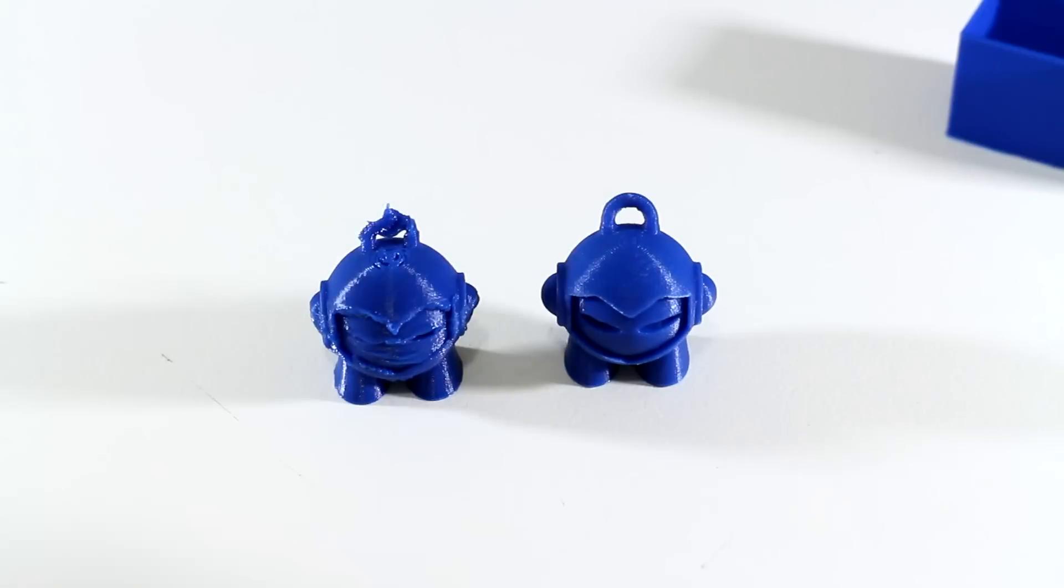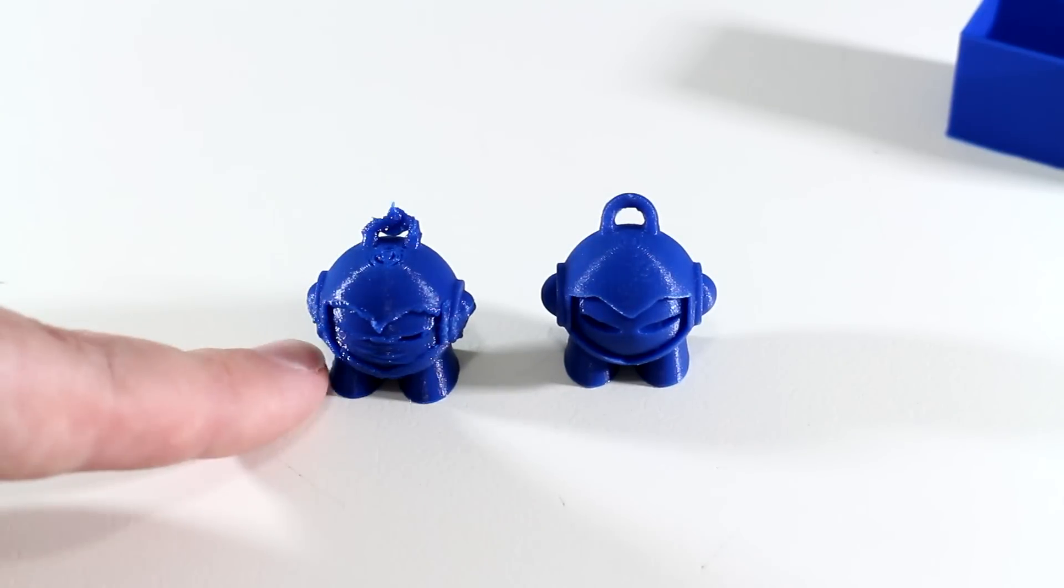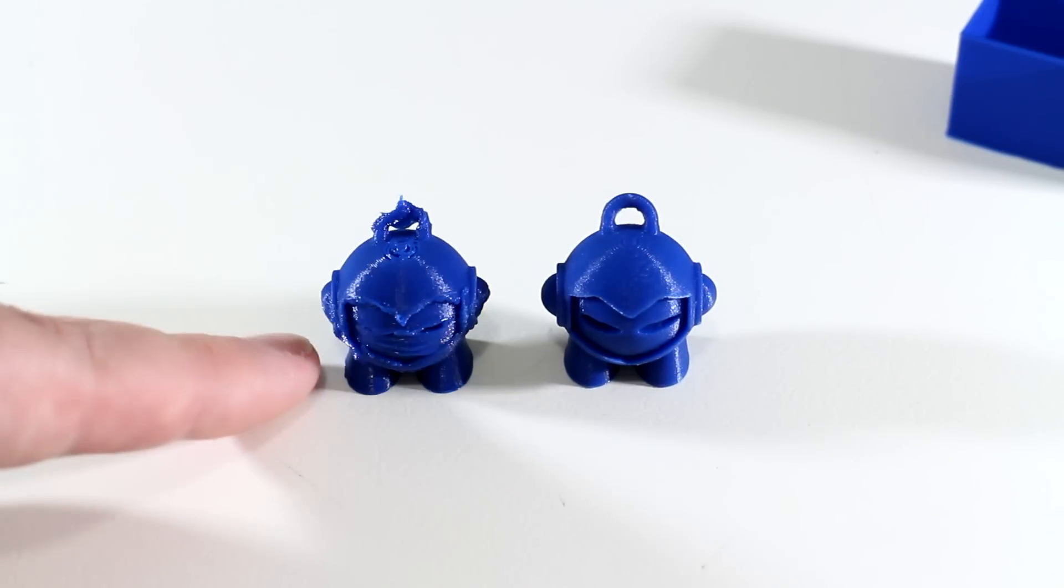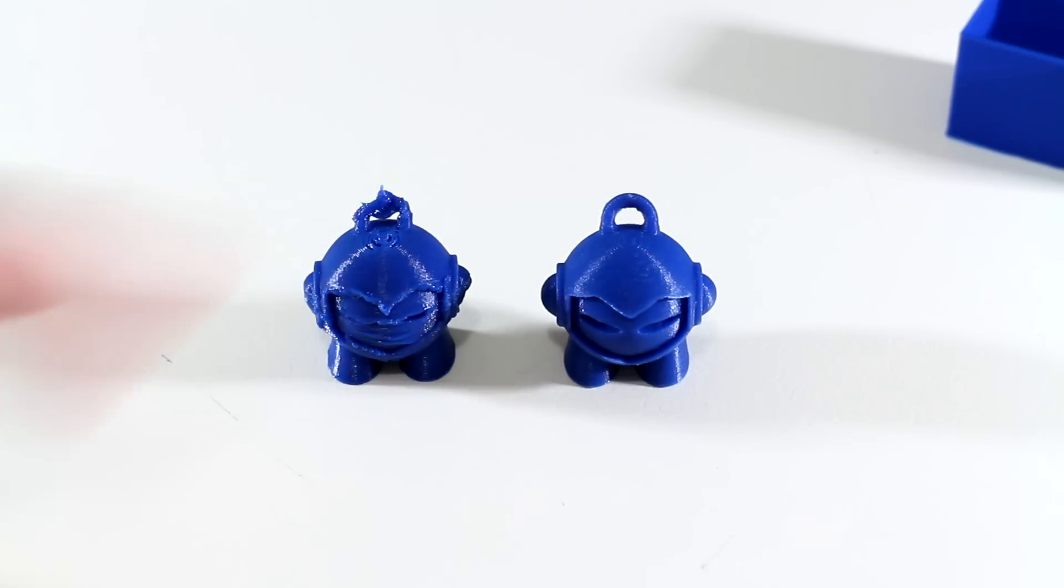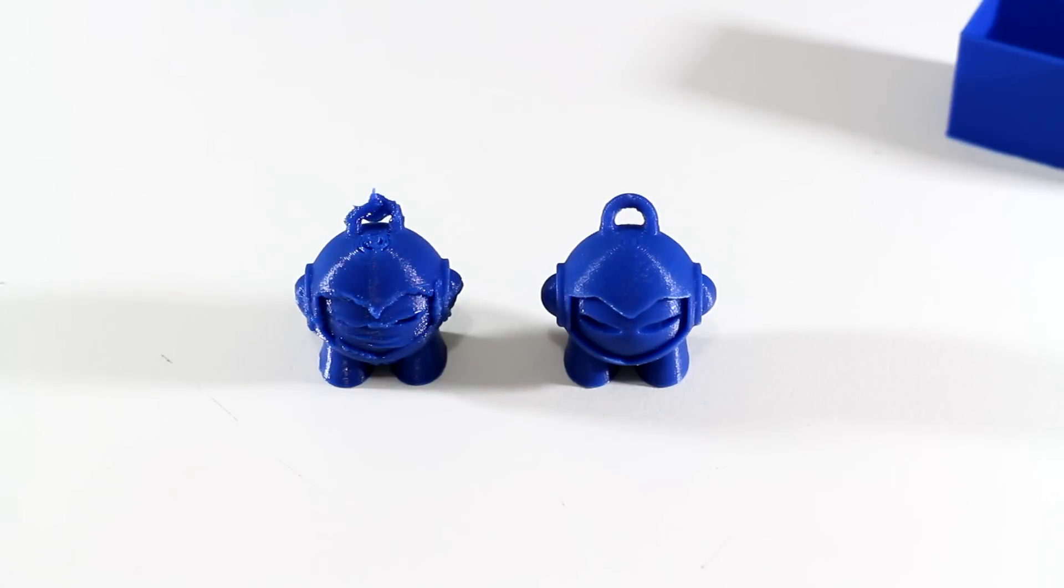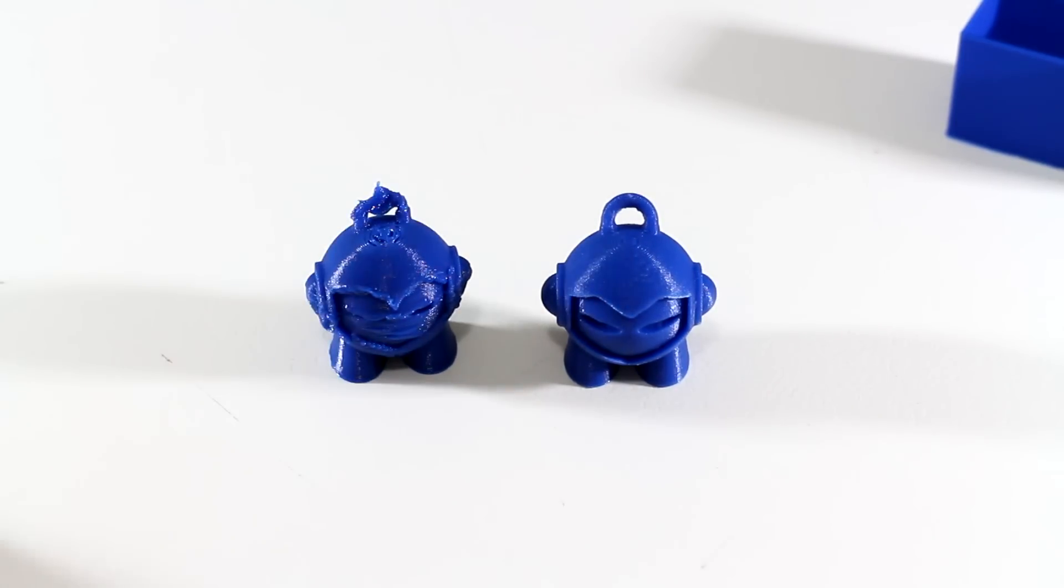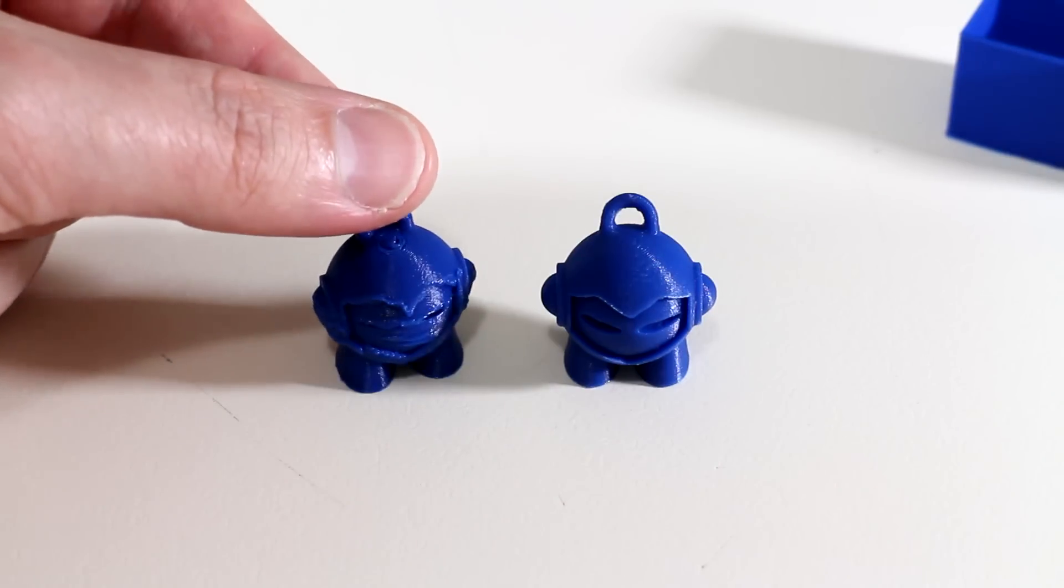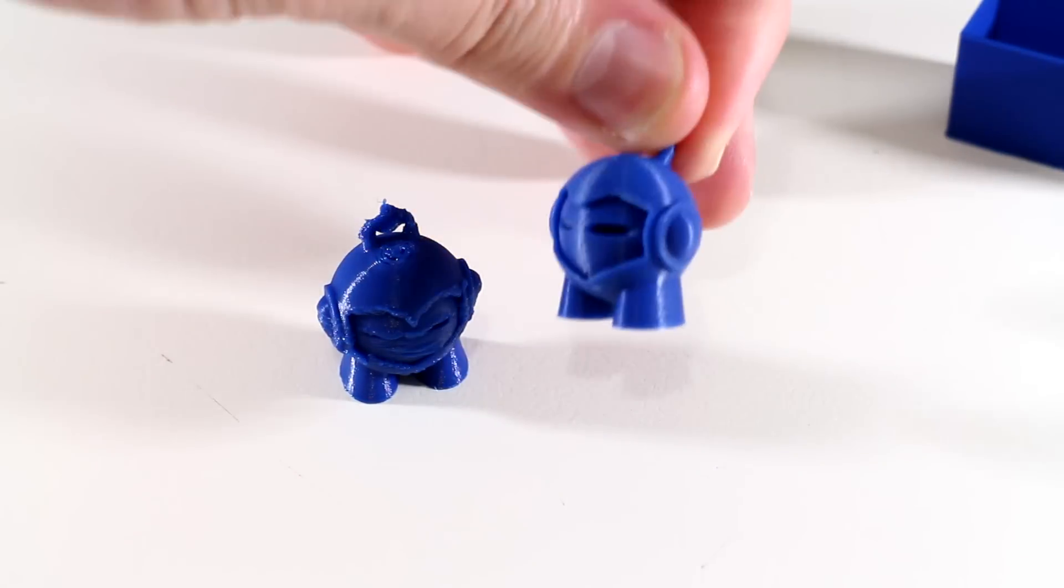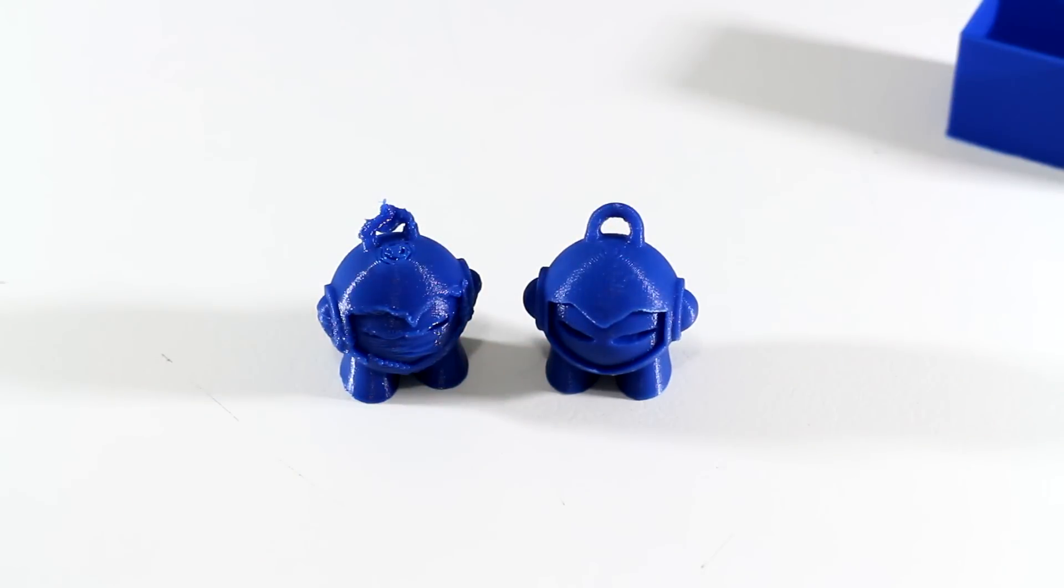So for this next test, I'll be printing Marvin once again with the black glossy ABS plastic I have. I'll enable the cooling fans, but only up to 50% speed. I wasn't printing this one at 100% speed because we don't need to cool the ABS down to that 55 degree mark like with PLA. We only need to cool it down to about 90 degrees. So, will ABS result in a finish like this? Let's find out.